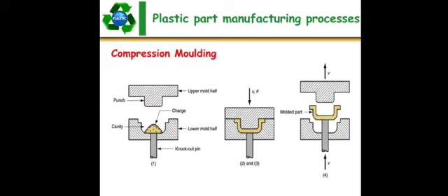The molding usually has a large projected area, so the closing force needed could be in the range of 100 to 500 tons and the pressure of 7 to 25 megapascals. The cavity pressure is needed.